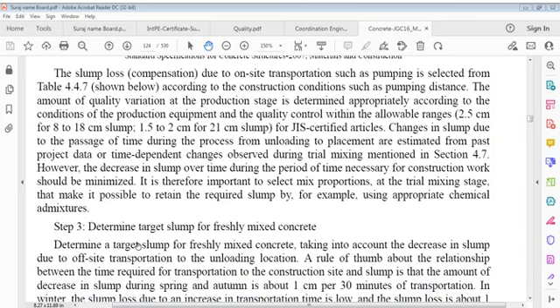The amount of quality variation at the production stage is determined appropriately according to conditions of production, equipment and quality control within allowable ranges, and that variation is 2.5 centimeter for 8 to 18 centimeter slump, and 1.5 to 2 centimeter variation for 21 centimeter slump. For changes in slump due to passage of time during the process from unloading to placement, these are estimated from past project records or data, or time dependent changes